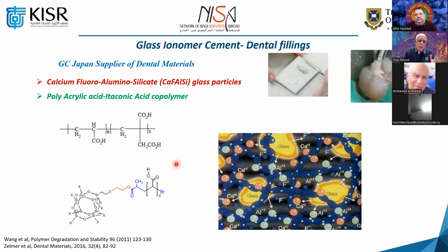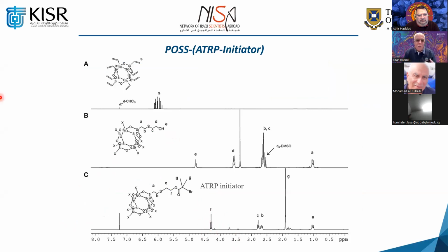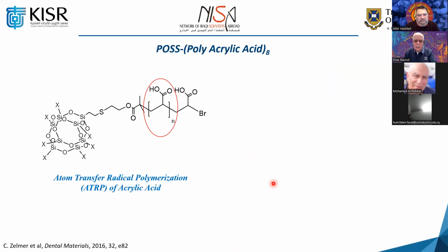So what we did, if you see here, we did some ATRP chemistry, same as before, and we attached polyacrylic acid. And we have a polyacrylic acid coming from this molecule. There is a carboxylic acid group from acrylic acid, a carboxylic acid group from itaconic acid, and a carboxylic acid group from this molecule which we produced. So when we combined all these three, before we show you some mechanical property, again, this is the NMR spectra before thiol-ene chemistry, which I showed you before, and then we introduced the ATRP initiator. The ATRP initiator is where we start the polymerization of acrylic acid from that. So all the chemistry is clean and nice.